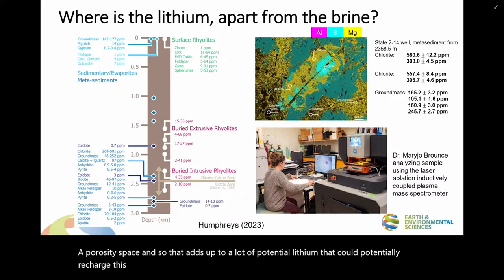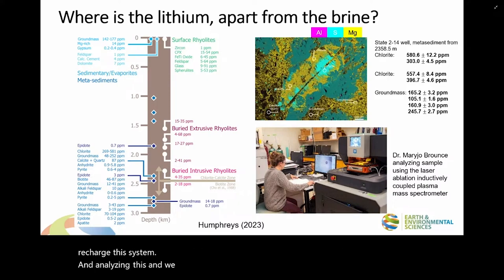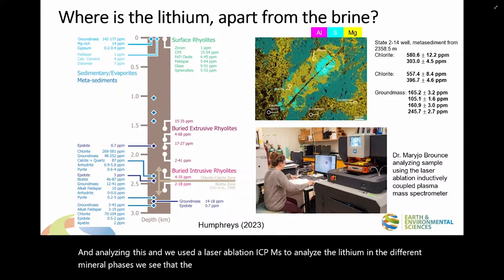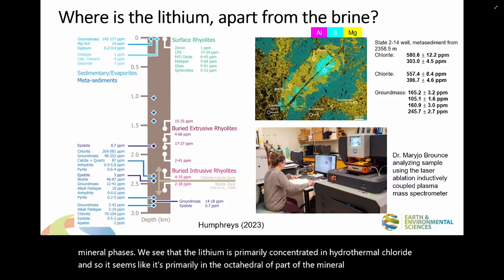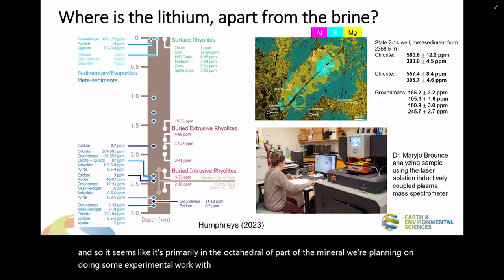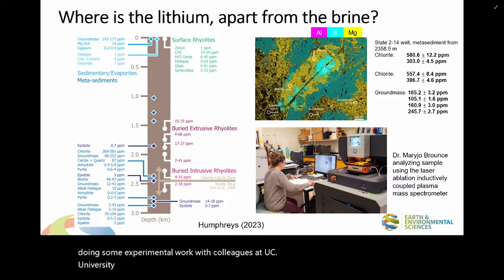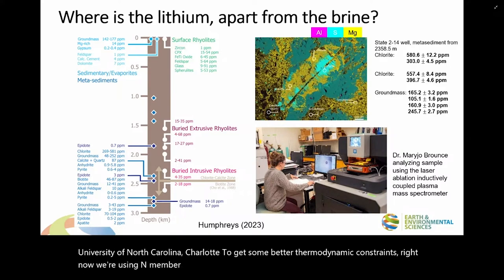In analyzing this, we used a laser ablation ICP-MS to analyze the lithium in the different mineral phases. We see that the lithium is primarily concentrated in hydrothermal chlorite. And so it seems like it's primarily in the octahedral part of the mineral. We're planning on doing some experimental work with colleagues at the University of North Carolina, Charlotte, to get some better thermodynamic constraints. Right now we're using end-member values for cookeite, which we are not sure is really an appropriate end-member because of the issues of solid substitution.